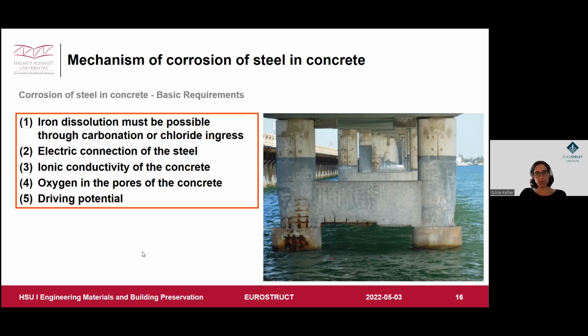So probably for bridges, or the very high probability for bridges, as soon as we have depassivation, we will also have initiation of corrosion. And keep in mind, all these 5 basic requirements need to be fulfilled at the same time. If we are able to exclude one of these basic requirements, no corrosion can take place. And this is just a clue on how to repair the structures and how to prevent ongoing corrosion.